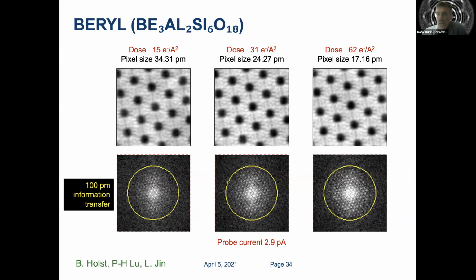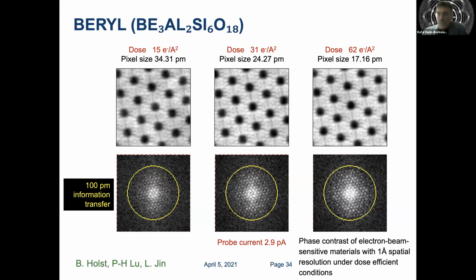And this means that at biological doses, we are getting close to 1 angstrom spatial resolution while being able to image very weakly scattering atomic columns with a phase-sensitive technique. In this case, integrated differential phase contrast, but it could be off-axis holography or it could be ptychography instead.